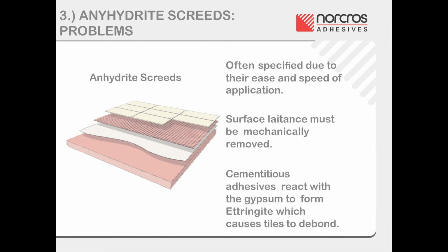Another disadvantage is that when a cementitious adhesive is applied directly to the screed, it reacts with the gypsum and produces a mineral called ettringite, which is formed at the adhesive and screed interface and is liable to cause the adhesive to debond from the screed. To avoid system failure, the problems which can occur when using an anhydrite screed should be taken into account, and the following actions should be carried out.